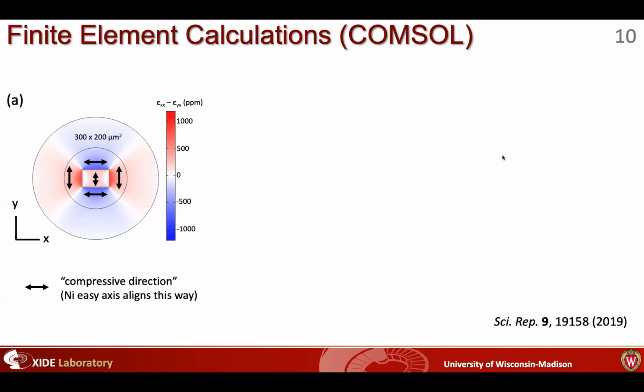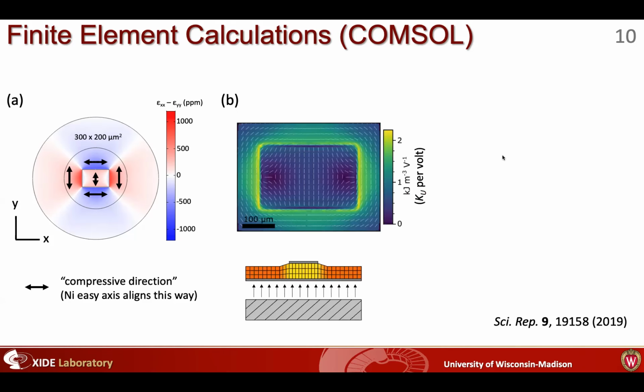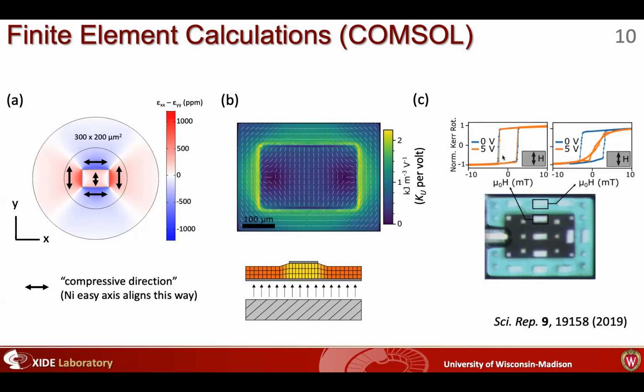But we also found that off the electrode area, we would see this other effect where we can get even more strain. So if you plot anisotropy energy with this color bar and the direction of the anisotropy that you would expect are these white lines, you can pattern the nickel both on and off the electrode and see that within the electrode area, you get an easy axis along the short edge of the electrode. But with voltage just off the electrode, you get the opposite effect, which matches pretty well with our COMSOL simulations.